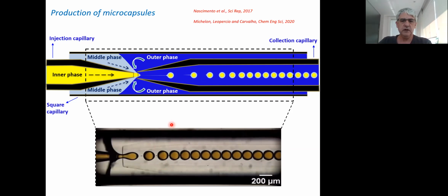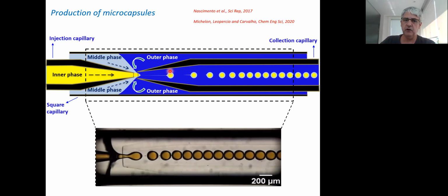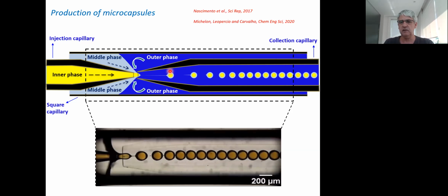And so we can control the mechanical properties of the shell by controlling what polymer system we are using, the thickness of the shell, because as these capsules are going to deform, you need to bend the shell of the capsules, and bending moment is a function of the cubic power of the thickness, and also the degree of cross-linking of the polymer.